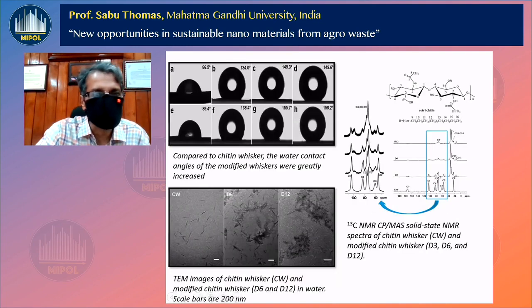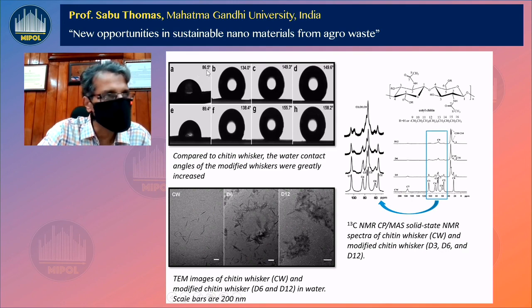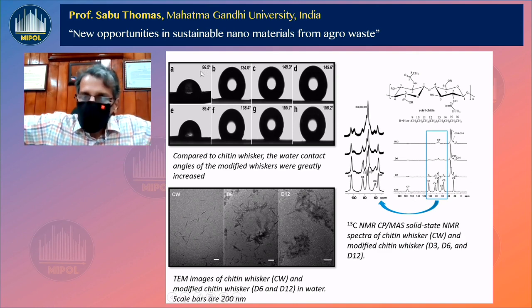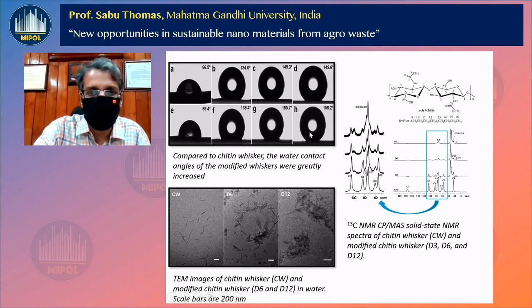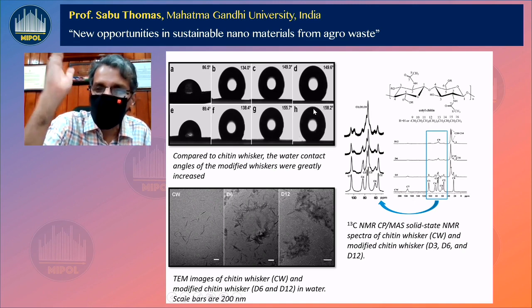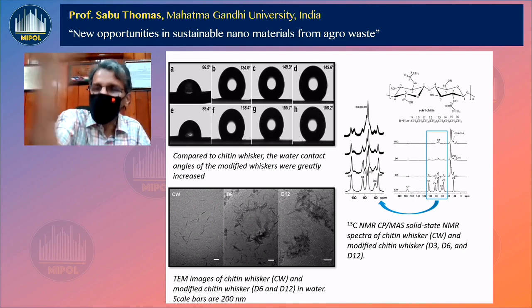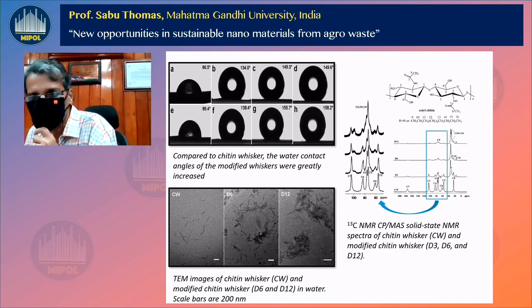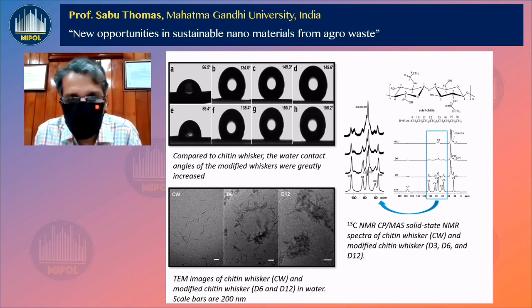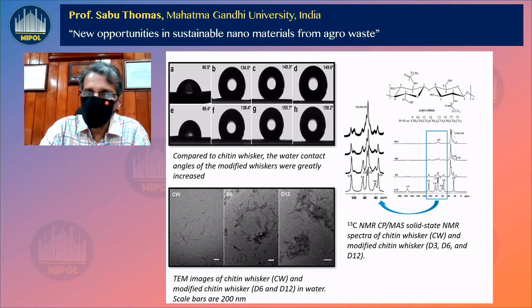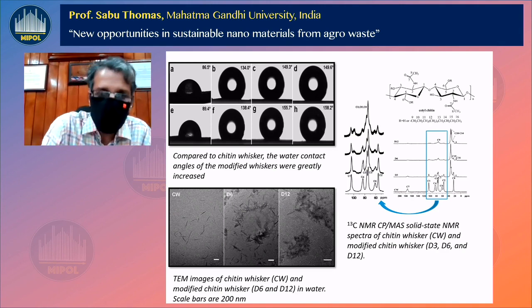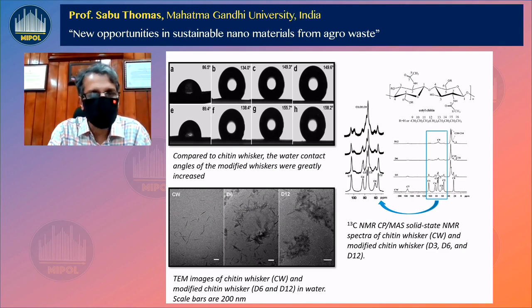You look at this. This is the nanochitin without any chemistry: 86.5 degrees, the contact angle. If you put an alkyl group on the surface of this chitin, you can achieve a 158.2 degree contact angle. You can make superhydrophobic surfaces. That's a fantastic material for structuring of oil. You can add this into oil to control the viscosity.